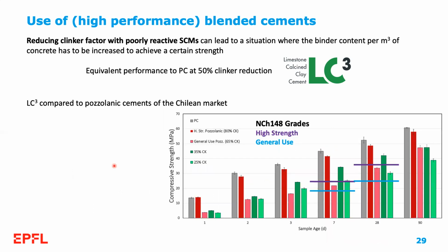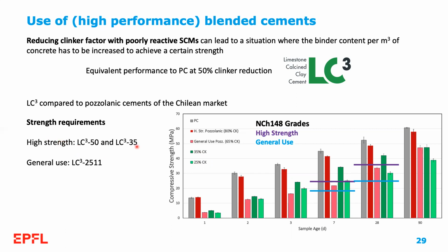If we then compare LC3 to pozzolanic cements of the Chilean market, both of the high strength and general use grades with 80 and 65% clinker, we can see that we can achieve the strength requirements of this standard with 35% clinker and 25% clinker if we use something like LC3. So we meet the high strength requirement of the Chilean standard with LC350 or LC335, and the general use one with actually LC325. There is a small typo there.